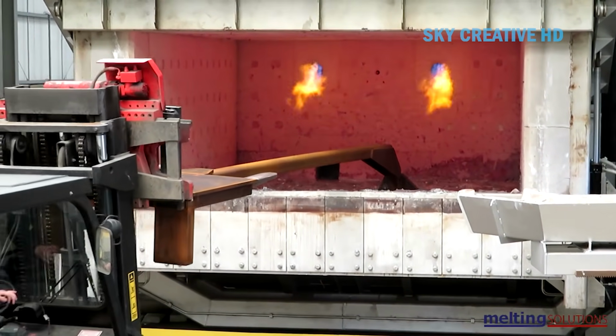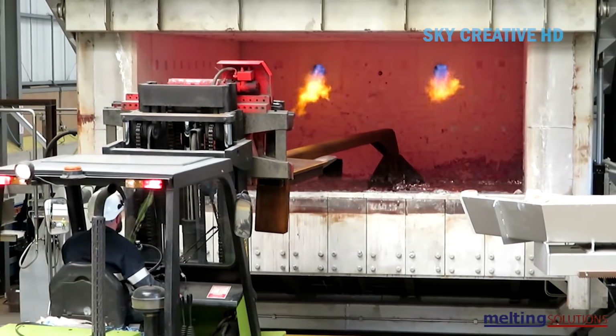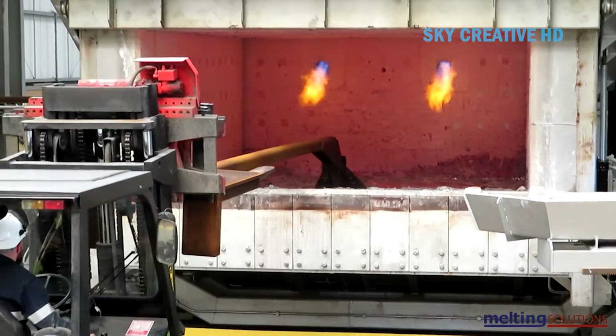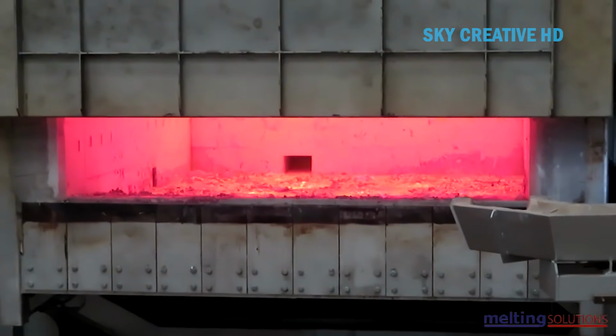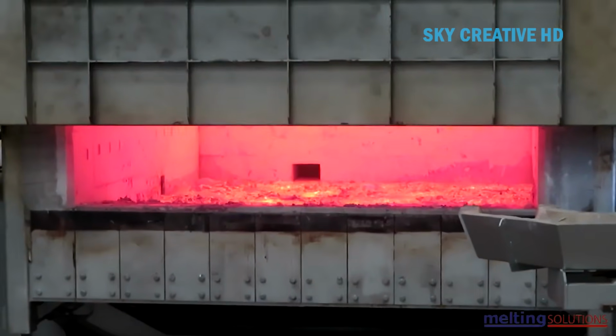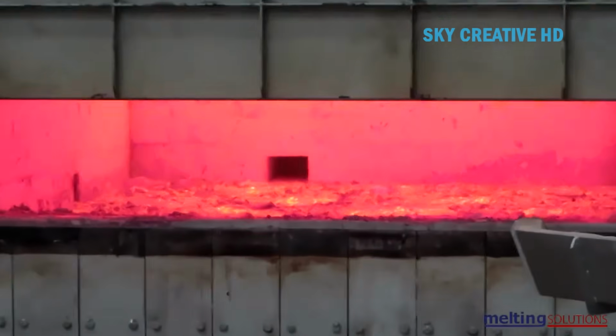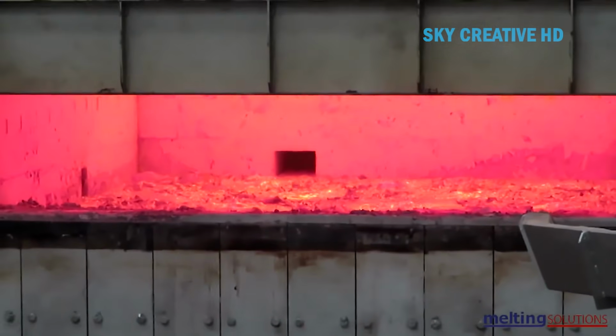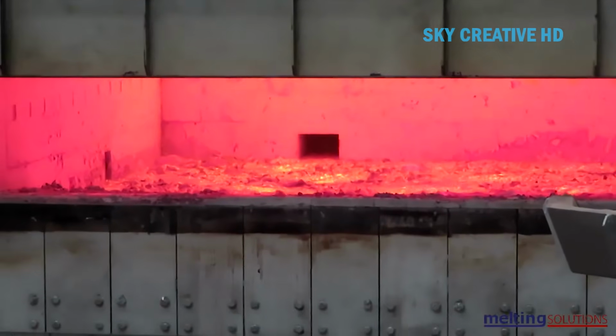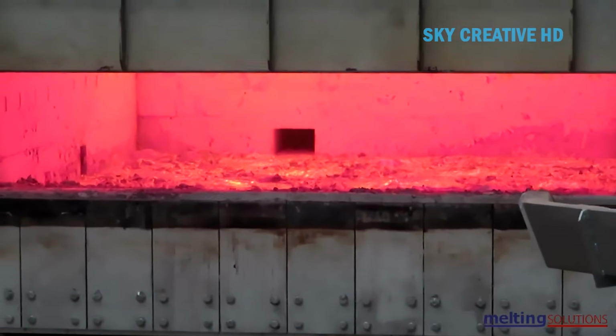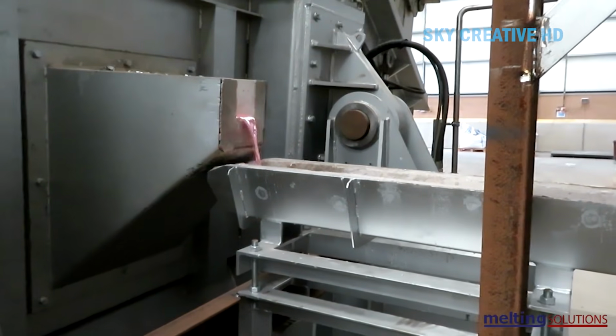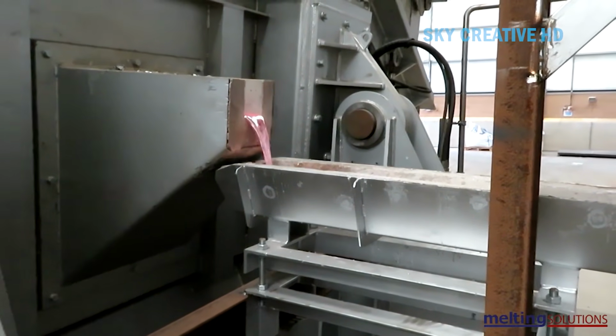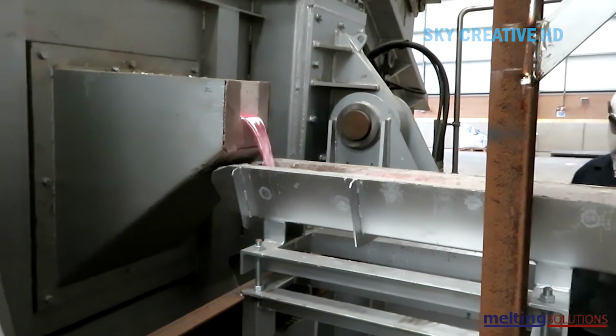From there, the scrap moves into the heart of the plant, the TR12 tilting rotary furnace. This is a 15 metric ton unit fired by an oxy-fuel combustion system, meaning it burns fuel in an oxygen-enriched atmosphere rather than regular air. The result is a dramatically hotter, more efficient flame that melts aluminum scrap far faster than conventional air-fuel furnaces.